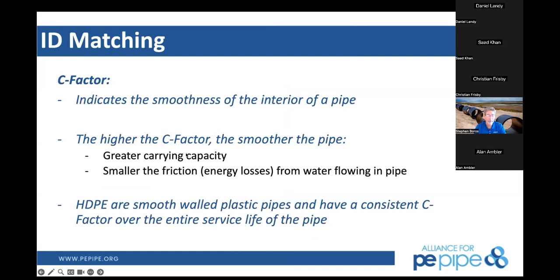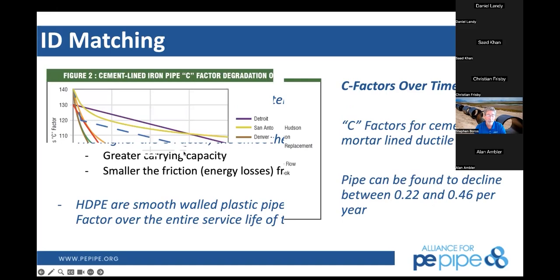So the higher the factor, the smaller the energy losses from water flowing through it, which, like I said, is what piping systems are for. For polyethylene, with a fused joint in it, that has a Hazen-Williams factor of 150 to 160. We usually use 150 just to be on the conservative side. But that's over the life of the system. It doesn't change. It doesn't degrade. It doesn't change at all through the life of that system. So your flow capacities and the fluid carrying capacities don't reduce.